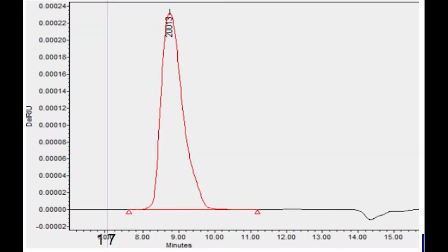Gel permeation chromatography was used successfully to confirm the 20 kilodalton molecular weight of our PEG samples.